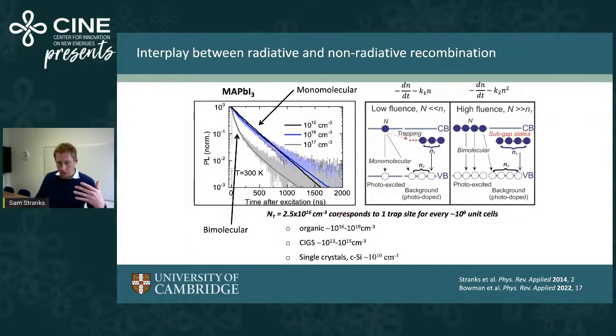And so for these films at the time, this is in 2014, these were trap densities of around 10 to the 16 per centimeter cubed, which is about one trap site for every million unit cells. This is quite low when we compare to organic semiconductors, for example, which are on the order of orders of magnitude higher. It's somewhat comparable to CIGS, but much, much higher than crystalline silicon, which is something like six orders of magnitude lower, and single crystals even of the perovskite.